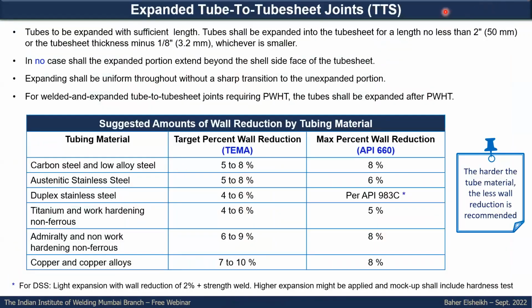Now for the requirement of the tube-to-tube sheet joint, the percent of the expansion. The percent of the expansion recommended depends on the material used. Some materials are subjected to work hardening, or some other materials might retain residual stresses that in future might cause stress corrosion cracking in service. That's why the percent of wall reduction, how much it will be expanded, depends on the material.